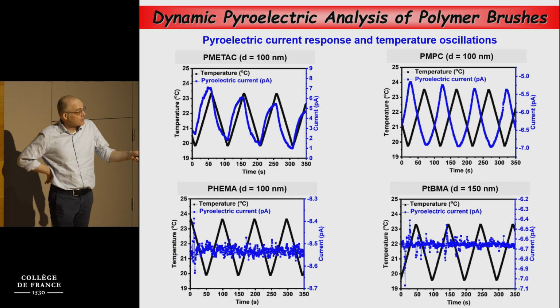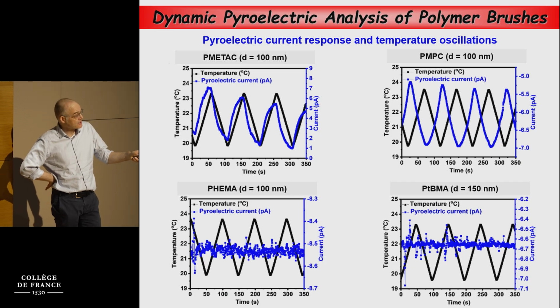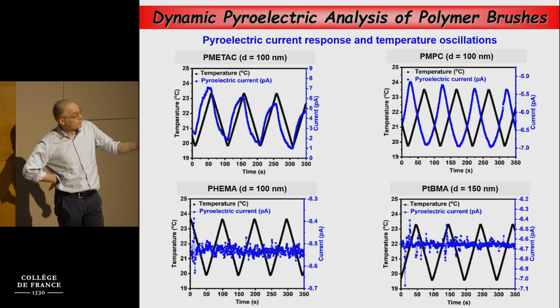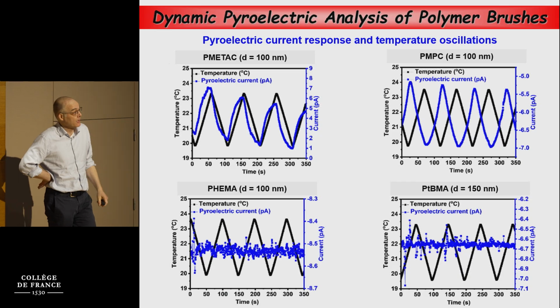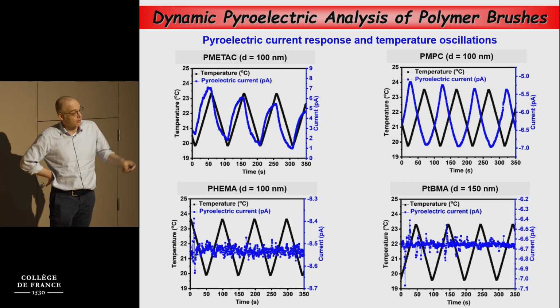If you utilize a hydrophilic hydroxyethyl methacrylate brush, there is no pyroelectric current. For a tert-butyl methacrylate brush, there is no pyroelectric current. But for these strong electrolytes and these zwitterions, we do measure a pyroelectric current of a few picoampere.